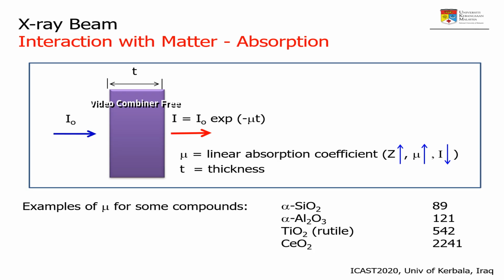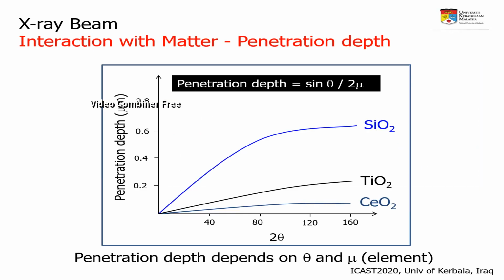The dependency of linear absorption coefficient on atomic number is best presented by titania and ceria. It is obvious that the linear absorption coefficient for ceria is 4 times greater than titania. As a result, the ability of X-ray to penetrate the material is reduced.